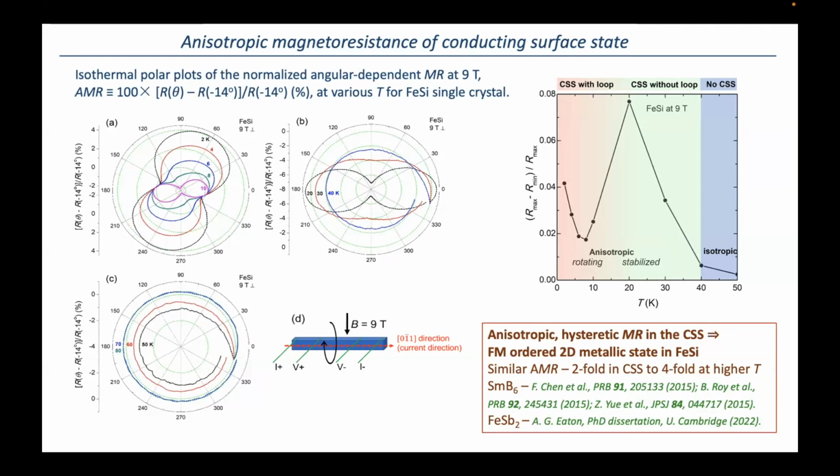Looking at the curve for 10 Kelvin, you start out at this point and it makes a butterfly-like shape. In fact, they all do in this temperature range. If you think about it as a butterfly, the wingspan of the butterfly decreases as you go from 2 to 4 to 6 to 8 and to 10 Kelvin, and the axis of the butterfly rotates clockwise. Then we go to the next plot that shows what happens at 20, 30, and 40 Kelvin.